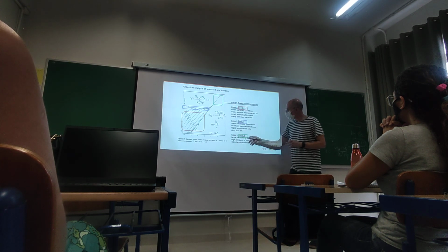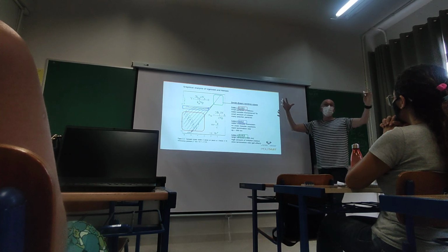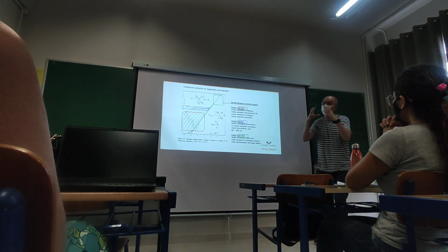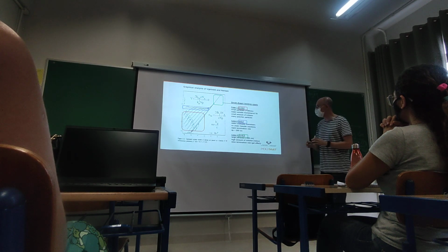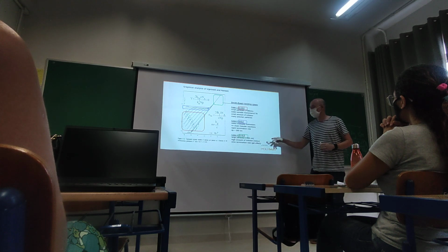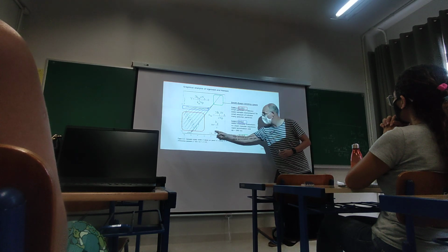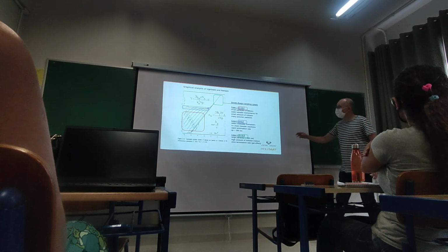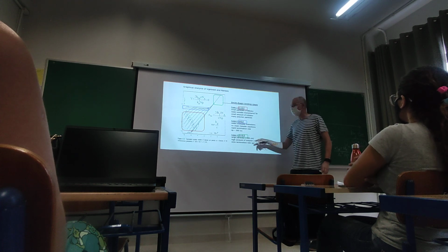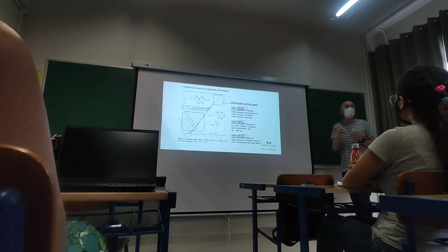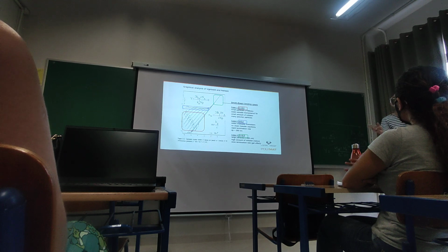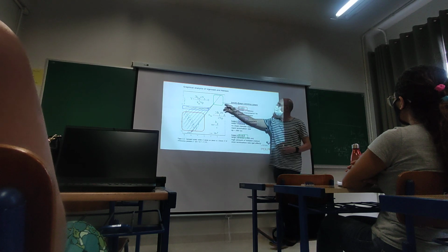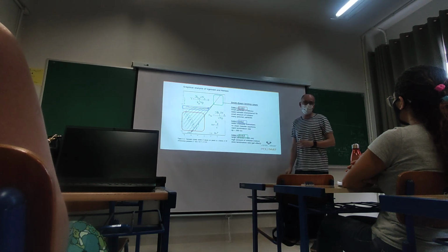And case 3 is achieved when we use very large particles. So with large particles it will be easier to have more radicals in the polymer particles. In the small ones it's difficult because termination will be faster. High amount of initiator, but normally redox systems, because we need alpha which is high, so we need high generation of radicals. Or we also need slow termination rates, and this occurs when you have gel effect. So if you have monomers like MMA that suffer gel effect, you can have a decrease in the k_t, and you will also be in this pseudo-bulk region.